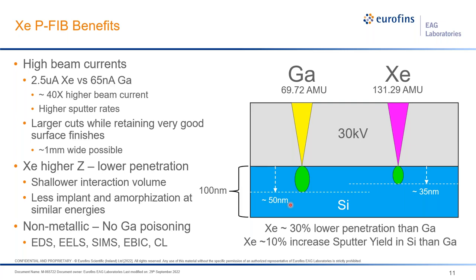And lastly, xenon is a non-metallic element, so there are none of the common gallium-related artifacts that we're used to seeing in our analyses, which enables better analytical data from your samples, especially for things like composition determination with EDS or EELS, and then further electro-optical testing of specific sites such as EBIC and CL.